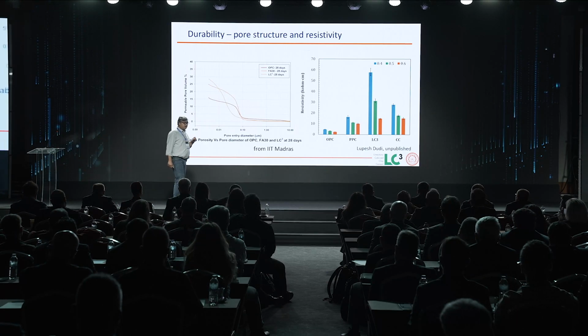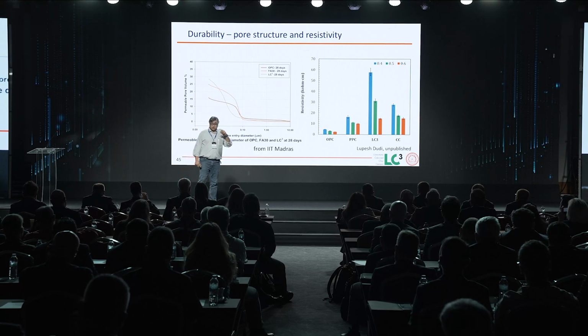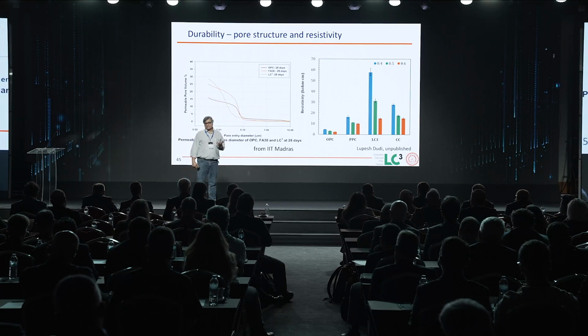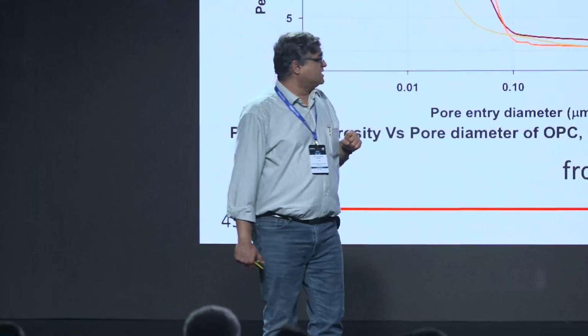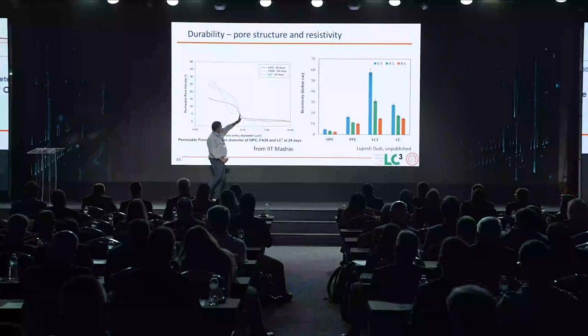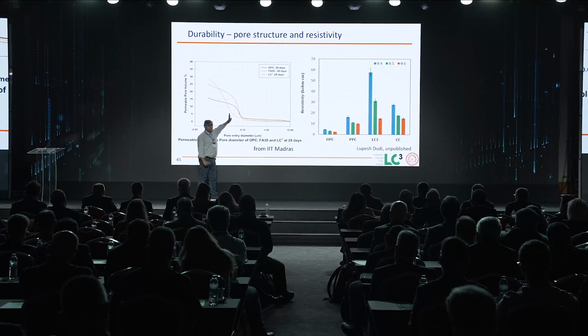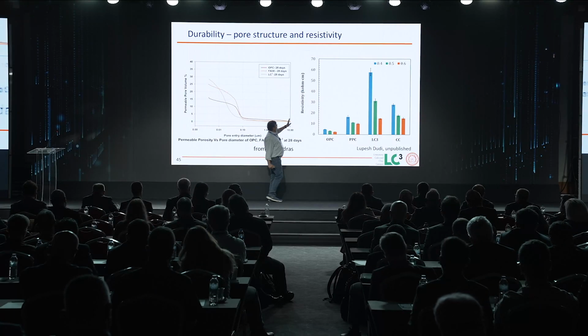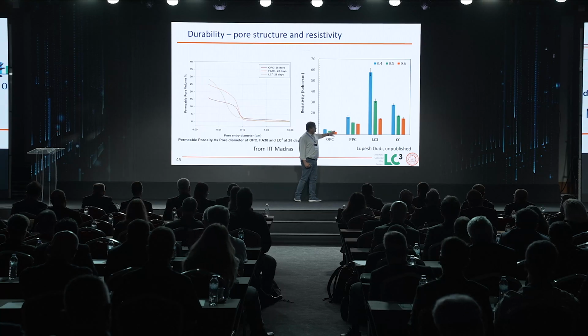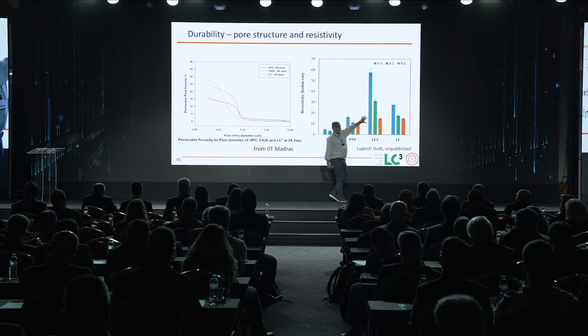The pores are finer, they're less connected, and the concrete has a lower permeability, lower chloride ingress, and so on. What this means is that the pores are finer. If you look at the mercury intrusion porosimetry graph, the breakthrough diameter of the pores is lower in the case of LC3. We've been seeing those results for a long time. What this also means is that the resistivity of the concrete is way higher.